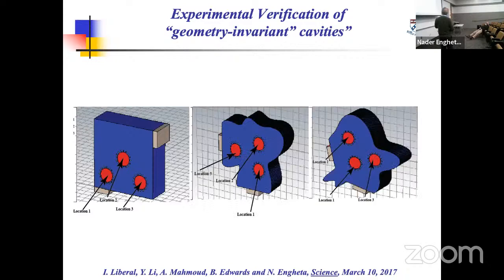So we built three cavities that you see over here. These three cavities, by the way, the shape is completely arbitrary. It's not like there are three specific shapes. We just chose three arbitrary shapes, but the cross-sectional areas are the same. That's the condition. And we put a dielectric rod inside. Now you see three rods, but the three rods just show the three rod locations. There's only one rod. For every experiment, we put it in one of these locations. So we did nine experiments over here.